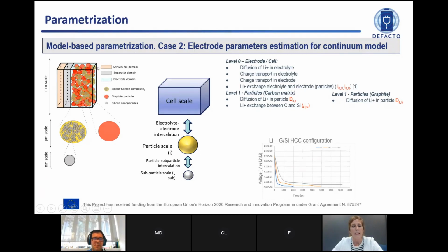So here, this is the half coin cell configuration with this graphite-silicon. We have the level 0 of the model, which is the typical equations of the P2D. Then we have the graphite, and in the graphite, we have the lithium diffusion along the particle. And then we have the carbon matrix, this is a representation of the carbon matrix, and inside, we have the silicon particle. In level 1, we will have the diffusion of the lithium along this carbon matrix, and then we include the lithium exchange between the carbon and the silicon. And we can even include another level in which we consider the diffusion of the lithium along the silicon.